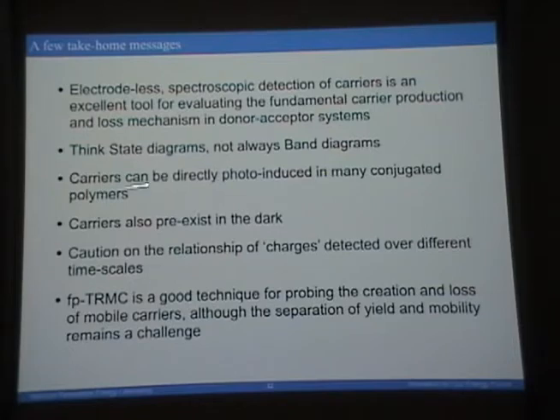Many conjugated polymers produce carriers directly without having an acceptor there. Why is that? Sean told us we had to throw away 1 volt of energy when we had an acceptor there. Not if you can do it with just the neat polymer. Back to the old semiconductor days. The Shockley-Queisser limit that Sean put up for an exciton binding energy of 0, right? We're getting closer to that. We can get a limit of 30% on our devices if we don't have to play around with acceptors.